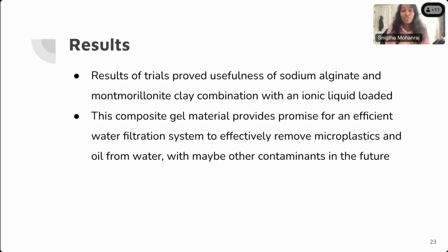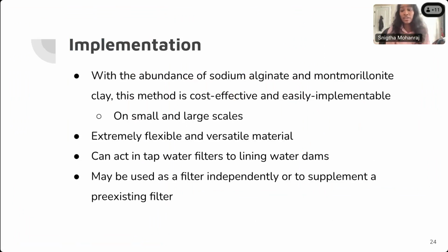And then again, the results just show that sodium alginate, MMT clay, and an ionic liquid is an effective way to remove microplastics and oil from water. And who knows, maybe other contaminants as well. So with the abundance of sodium alginate and MMT, this method is very cost-effective and easily implementable on both small and large scales. And the gel polymer is very flexible and versatile,